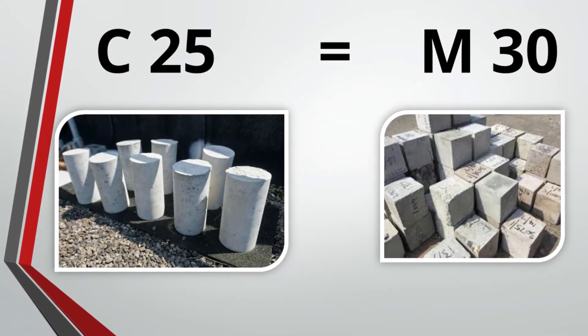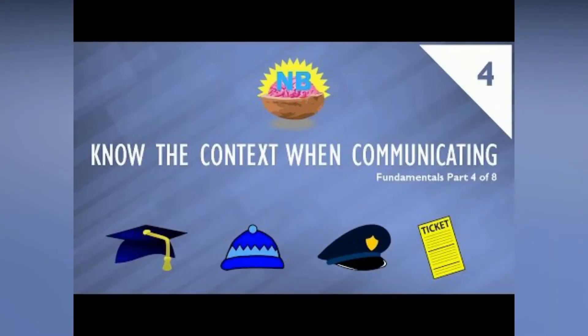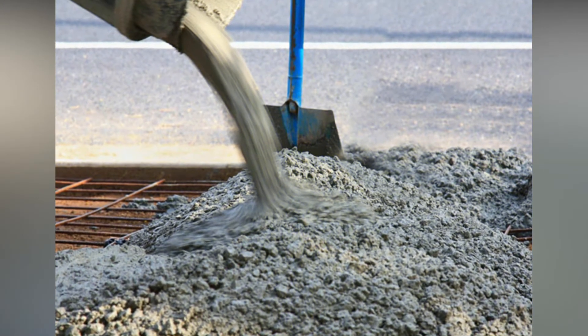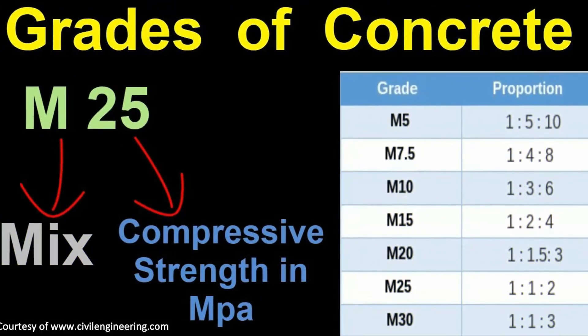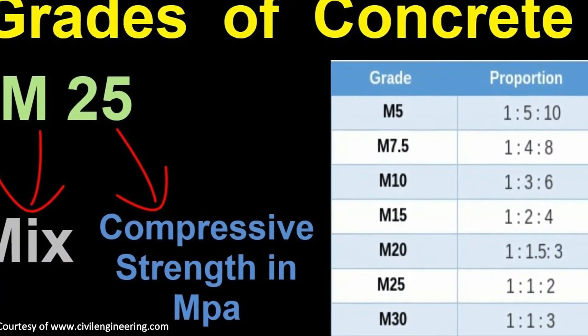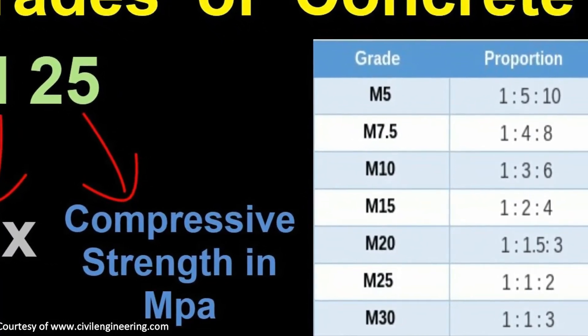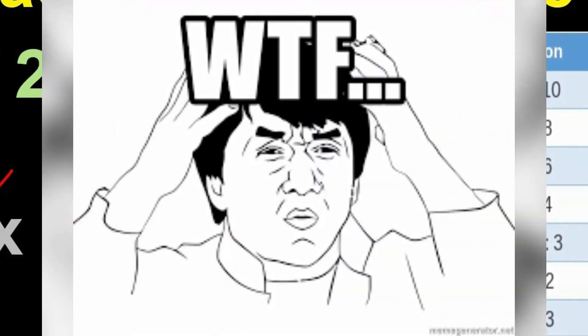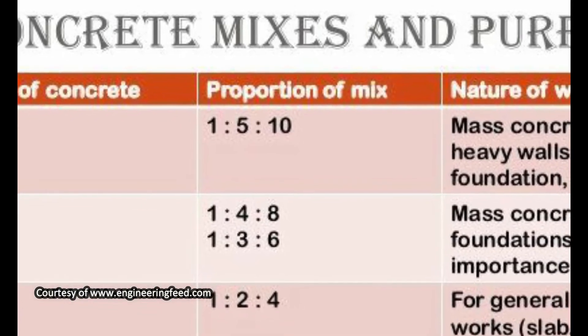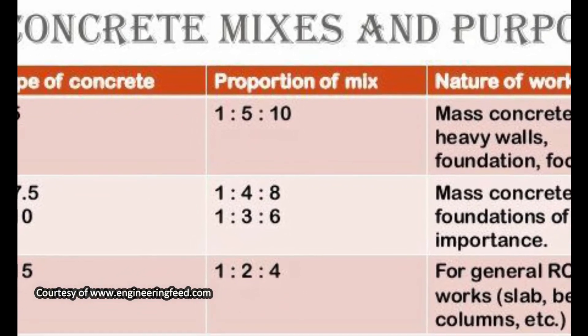It's important to know exactly what is being asked of you before you cast your concrete. If you make grade 25 concrete using a mix calibrated for cubical samples but you're in a region that uses cylindrical samples for quality control, you will have effectively produced grade 20 for that region — not grade 25 as you thought. Concrete mixes are a topic for another day.